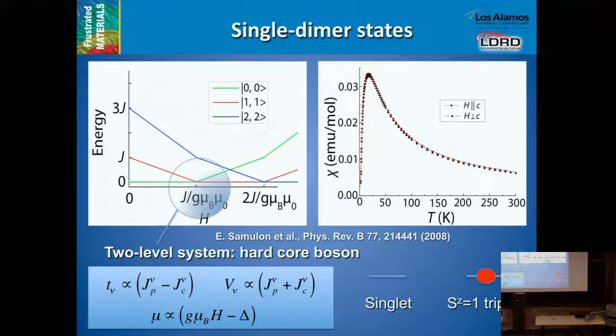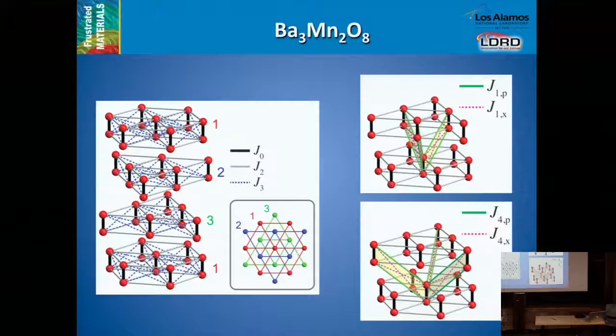Yeah. Right, it is true that by applying pressure, with uniaxial probably you will only separate the dimers, so you will increase the spin gap. But if you apply pressure in a way that you can get these guys closer together, yeah, you could induce a phase transition. So you could go from a paramagnet, a quantum paramagnet, as this is, into an antiferromagnet. It will be a different kind of critical point. Yeah, but it hasn't been seen. Not in this material, because here the spin gap is big. It is like 9 Tesla, so it's 10 Kelvin, right? Something like that. So it will take a very high pressure to close that gap in this material. But there are other materials where they can close.